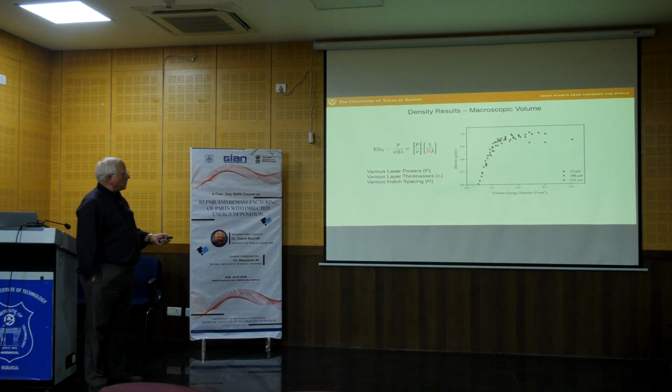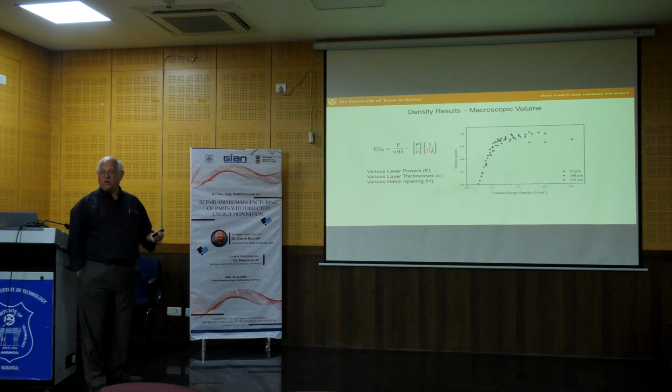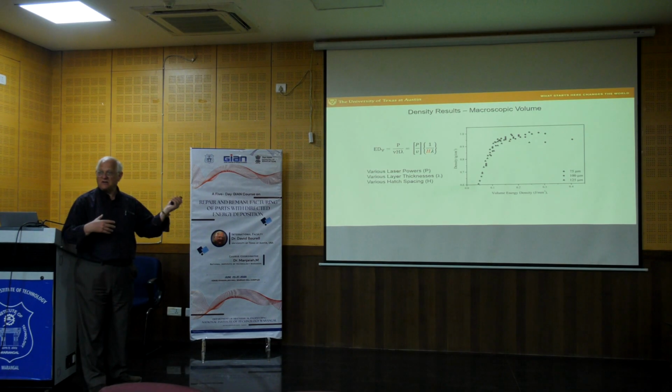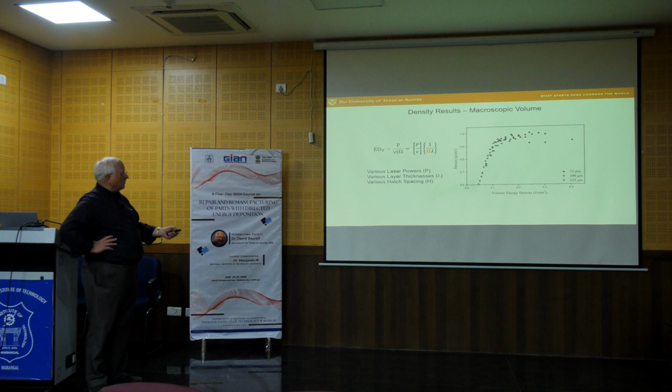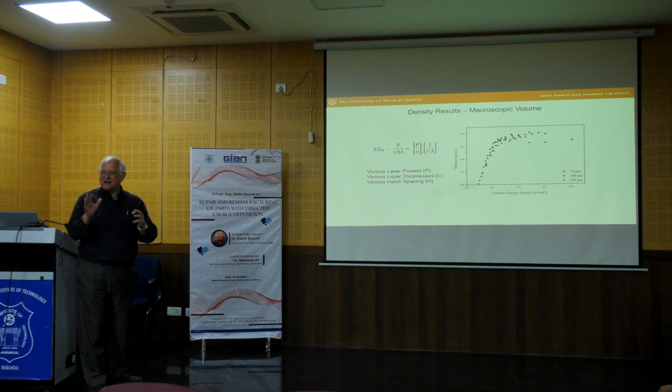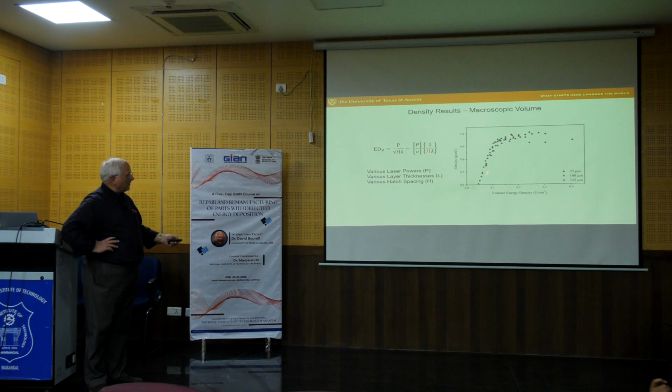And what we want to see on this plot is that for a given energy density, I'd really like to have a one-to-one correspondence, right? So you tell me the energy density, I tell you what the density is. And so we see that it really works pretty well. Maybe out here at high energy densities, it works not as well as it does at low energy densities.